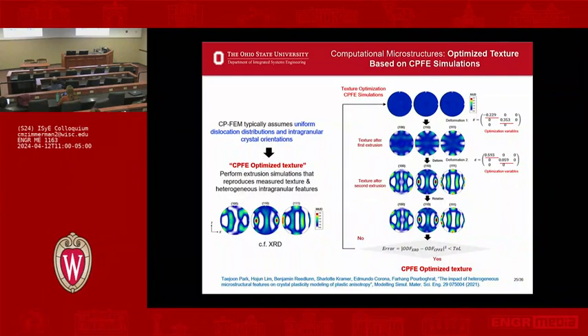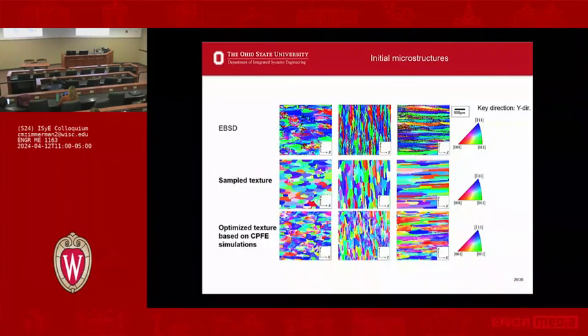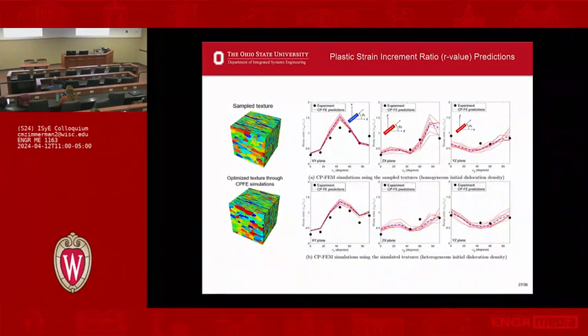Once we did, this gave us the residual stresses. We then created another model, which we call the optimized model. So this is the original one, I mean, this is the EBSD, the original experiment. This is the sample without that. This is when we put those residual stresses into it. It starts to become a lot more like that. And then when we use this model, it actually predicted things. This is a sample texture just to optimize. We could see that it actually corrected even that error. All of these models are bringing you more and more into trusting the data that you can create.